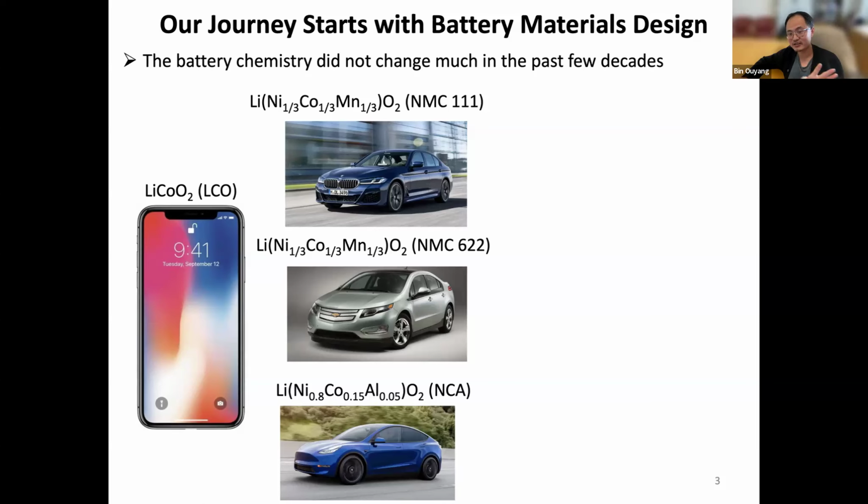We actually joke about it as the NMC curse. The reason is that if you want to work with a battery, especially a layered-based battery cathode, what's going to happen is that when you move lithium in the lithium layer, there is a chance that the transition metal is going to pass through the tetrahedral bottleneck site and go to the lithium layer, because you're going to evacuate the lithium layer when the battery is cycled.